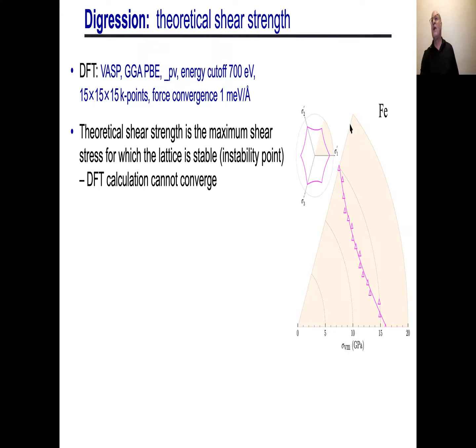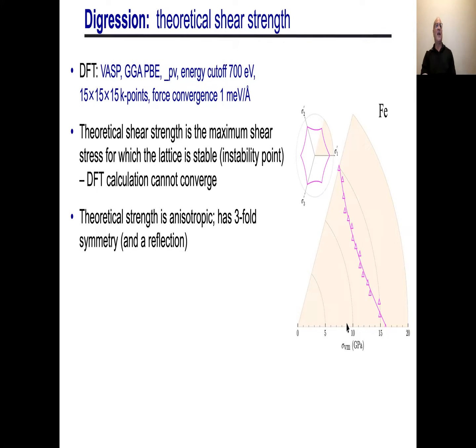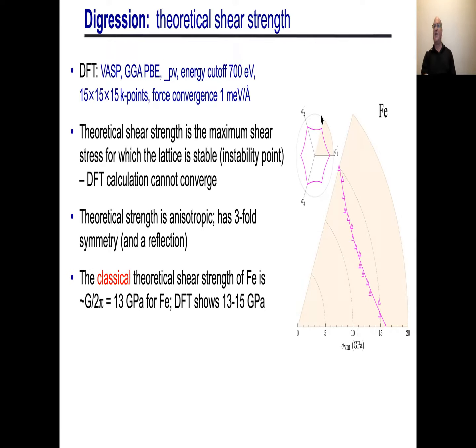But the point is, what I'm showing you here, again, is the deviatoric plane. Again, these are the projections of the eigenstresses, or the principal values of the stress tensor. And these are actually data points, and the curves shown here. I'm just showing 1/6 of the circle because I know the symmetry. The point I'd like to make is the theoretical strength here is at least about 13 or so GPa in terms of the von Mises stress. So it's quite substantial. And this theoretical strength curve has threefold symmetry plus a reflection. So that's how we get this curve here.